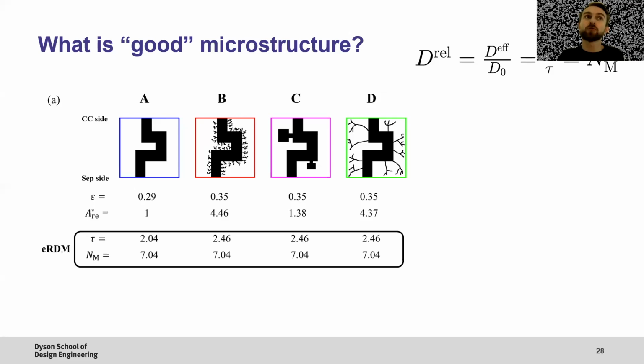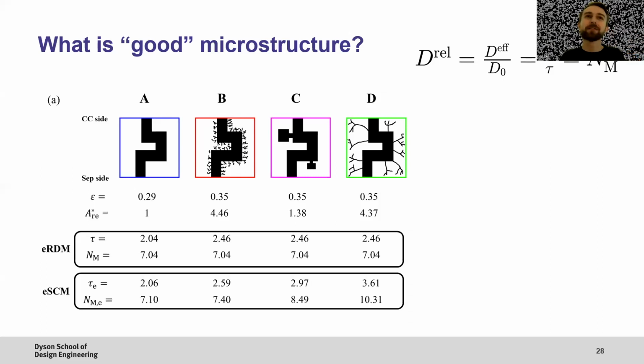If we use the conventional tortuosity factor, actually B, C, and D, because we designed them that way, all have the same tortuosity factor. And because of how the MacMullin number is calculated, which you can see in the top right, actually all 4 have got an identical MacMullin number, which is very satisfying indeed. So all that's describing is, considering how much volume fraction of pore you've got, how easy is it to get from bottom to top? And the really exciting thing is, using our method, it's not trying to get from bottom to top, it's trying to get from the bottom, the separator, to the surface of the nearest white region based on conduction, so sort of Nernstian stuff, as well as capacity at the surface.